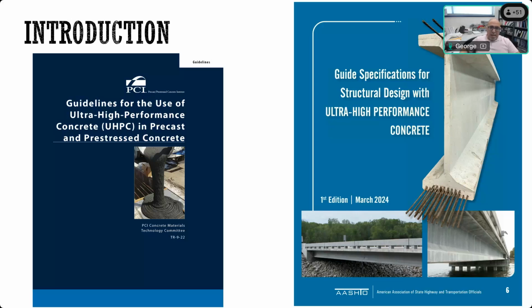And as you can see from the picture, even on this cover here, you see how thin the web is. And this web is with UHPC, you don't need to add reinforcement. You don't need even to add reinforcement in the bottom flange or top flange because of the fibers that are within this material and give it some kind of reinforcement. So it can basically reduce significantly the amount of conventional reinforcement in concrete.